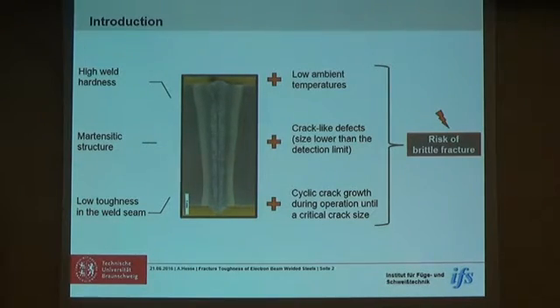If we think of beam welds in structural steels, we usually think of relatively high weld hardness compared with a monolithic structure, and thus low toughness in the weld seam. If we use those welds in low ambient temperatures and we have crack-like defects due to the production process, the welding itself, cyclic crack growth can occur due to cyclic loading during operation until it reaches a critical crack size, and there is a risk of brittle failure for these components.